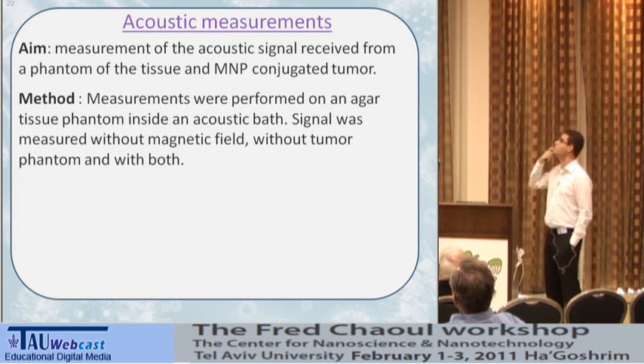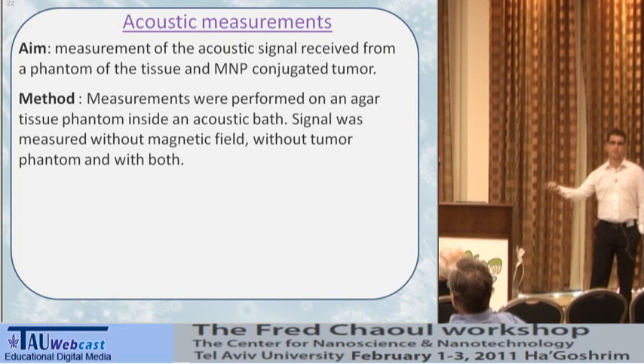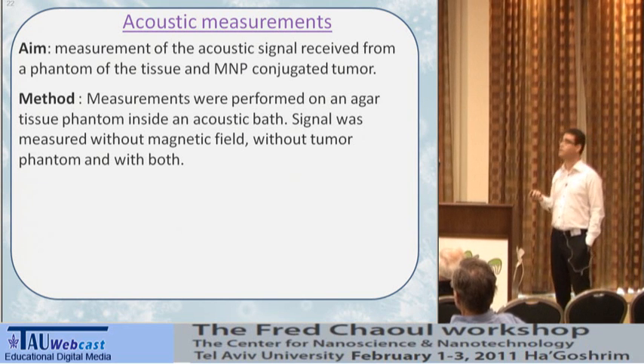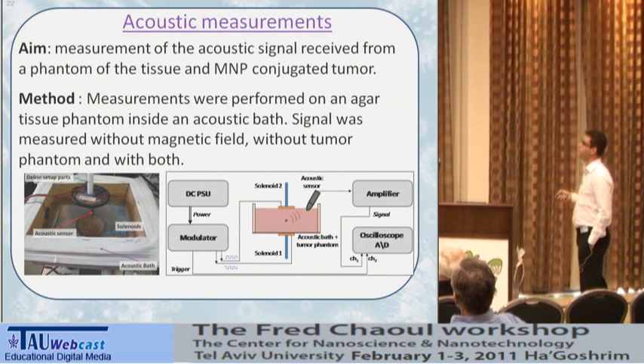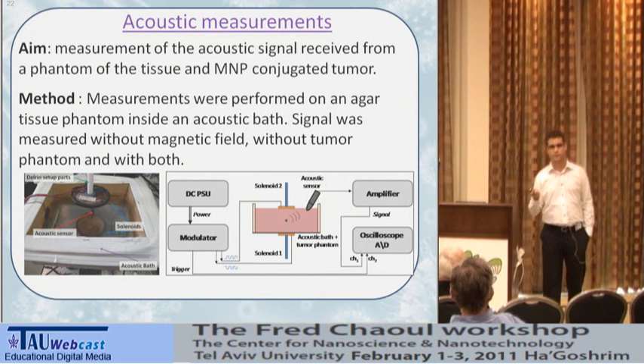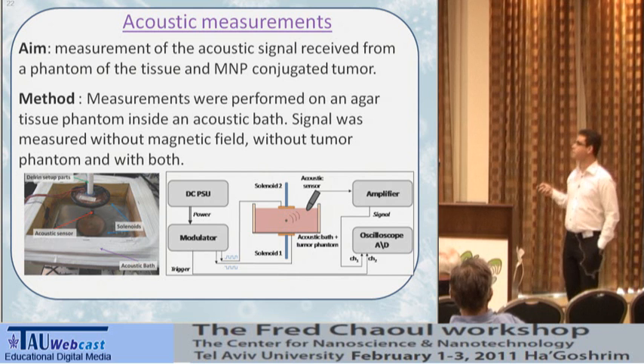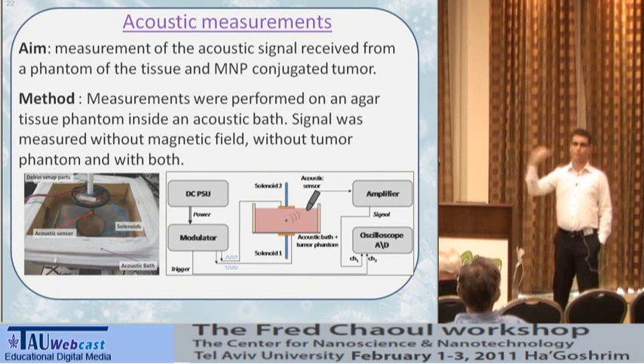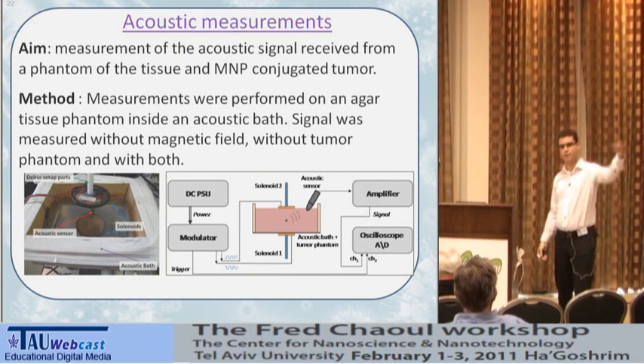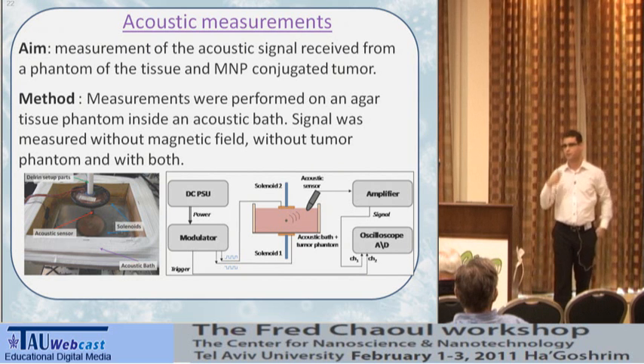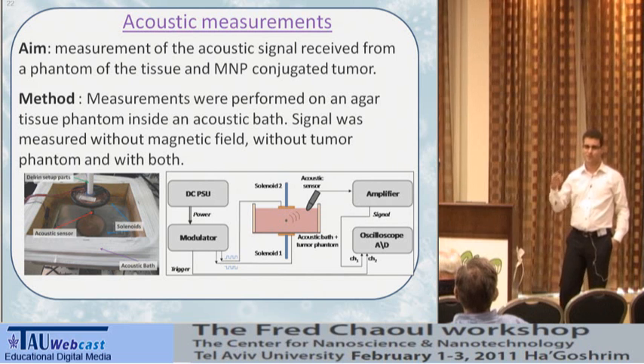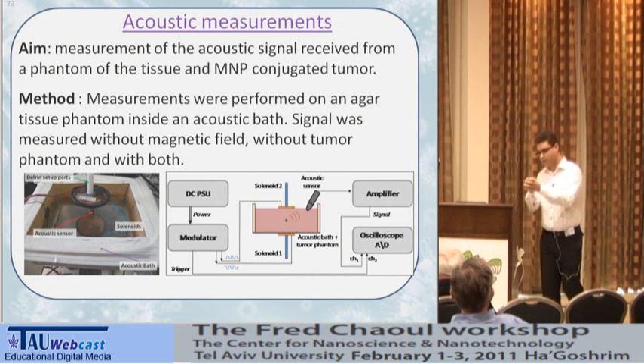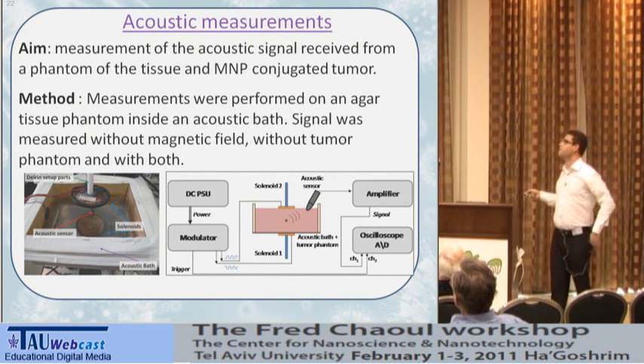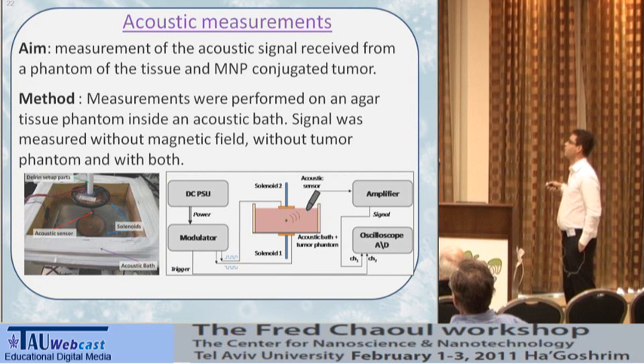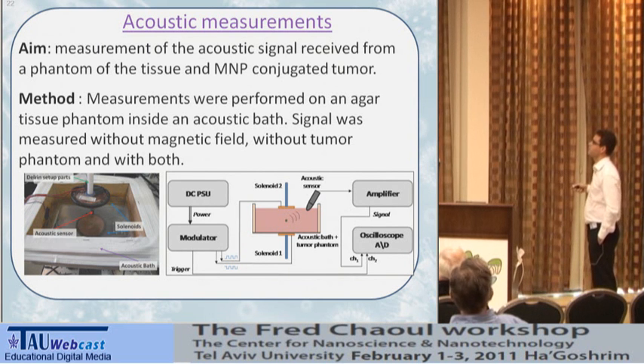In the second experiment I'm going to show you, we wanted to see what acoustic signal we get from a tumor phantom. So we built an acoustic bath. The acoustic bath simulates the tissue in the sense that it absorbs the outgoing waves, so they won't bounce from walls. When I speak to you here, the acoustic wave bounces from the walls, and we have reverberation. It goes back and forth. We wanted to cancel this reverberation because in real life the acoustic wave just propagates outside and doesn't bounce off. So we built this acoustic bath. We placed our solenoids, and we placed a tumor phantom made of agar gel with nanoparticles and an acoustic sensor.